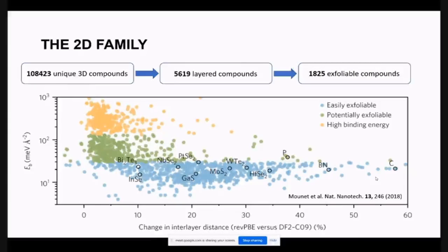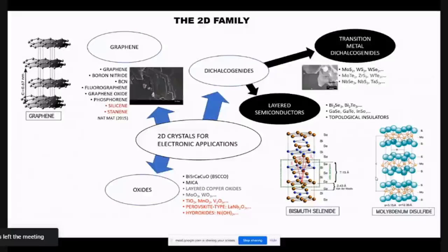Now the family of these materials is, in principle, what can be exfoliated, and look at the numbers here. If you have a typical binding energy between two layers of approximately 10 to 20 milli-electron volt per square angstrom, it's easy to exfoliate. That means you take two tapes and you just cleave the material and it will form nice layers along a lattice plane. There could be about 1825 according to calculations now. So imagine the phase space, of which we know probably about 30 to 35 can be separated, exfoliated, stabilized and made into devices today. And this number is increasing.